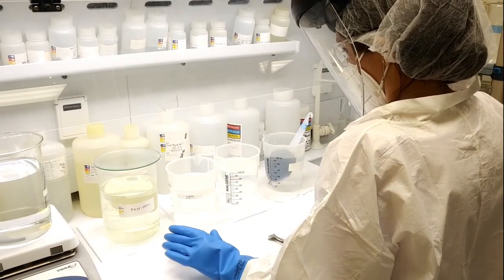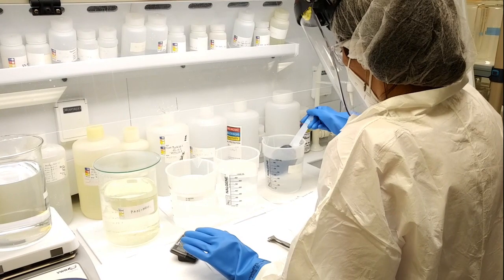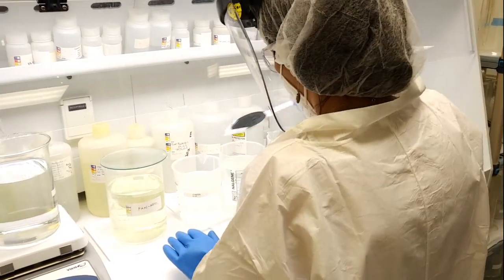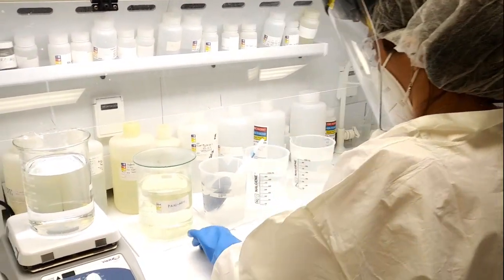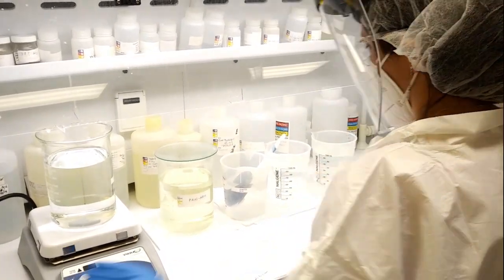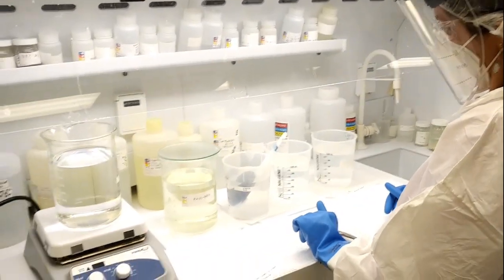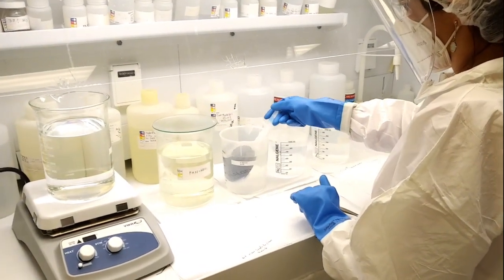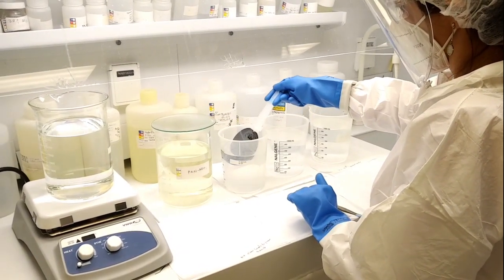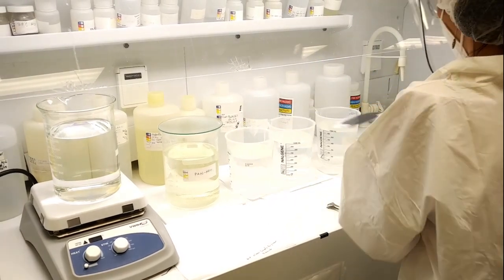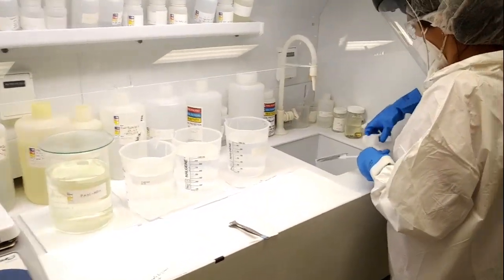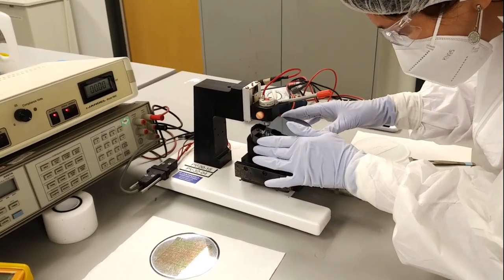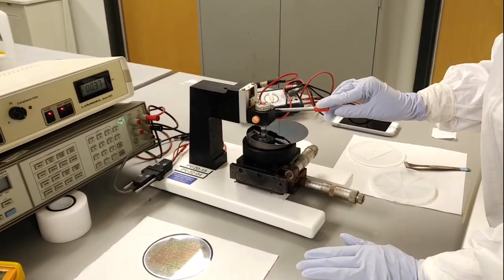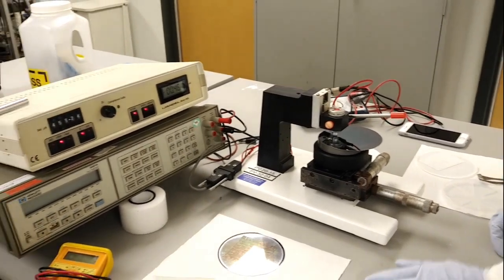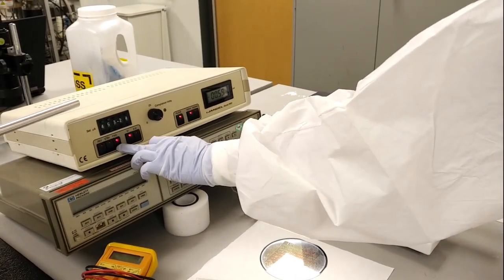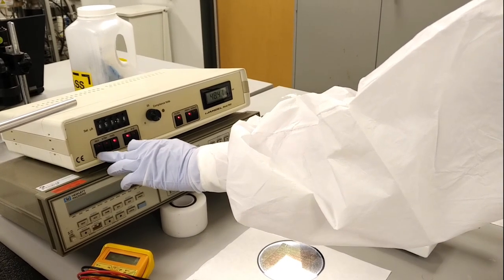Bringing the wafer to the wet bench, the spin-on dopant is removed from the wafer by dipping it into a 10% hydrofluoric acid solution for about 5 seconds. The wafer is then dipped in DI water to stop the etching process. At this point, the spin-on dopant has been removed from the wafer, but the mask is still in place. Some of the wafer is oxide mask and some is doped silicon. The wafer can be checked for successful doping by measuring the sheet resistance of the wafer. A drop in the resistance indicates the doping was successful.